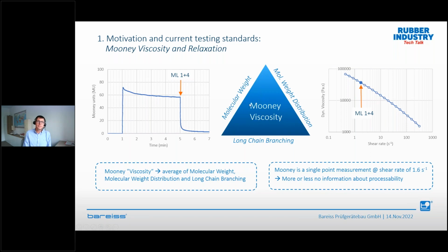So for example, if we go to polymers, the Mooney is an average of molecular weight, distribution, and long-chain branching. These are the three main factors which can be changed in a polymer. But Mooney is an average of all of them. So you can have a higher molecular weight, but maybe a broader molecular weight distribution, but it's the same Mooney viscosity. Yeah? So that is something we would like to work out a little bit more. The advantage is well known, but the disadvantage is it gives less information. Yeah?